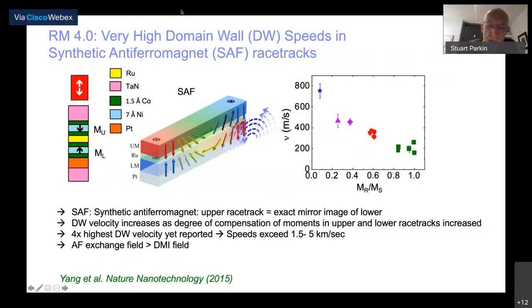And it turns out when we invented this just 3 or 4 years ago, we discovered that this coupling, the antiferromagnetic coupling through this ruthenium layer, leads to a new type of exchange torque, which is very large and accelerates the domain walls, enabling us to achieve domain wall speeds of more than 1 kilometer per second when we pass current through the racetrack. And this is what makes racetrack interesting today. It's key that there's no net magnetization, no dipole fields, and that the domain walls can be moved at these super high speeds. So I believe this makes it possible to build, for example, a static random access memory replacement by using a racetrack which is extremely short, 100 nanometers or less in length, in which we have a single domain wall moving backwards and forwards, and we can detect it using an integrated magnetic tunnel junction.